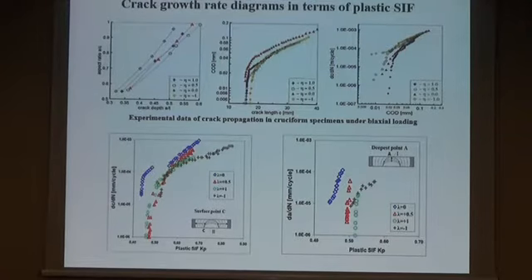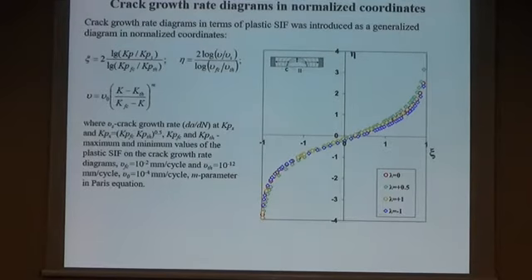So I believe that this result demonstrates the advantage of plastic stress intensity factor application as a characteristic of fracture resistance material properties. And crack growth rate diagrams in terms of plastic stress intensity factors in this study were introduced as a generalized diagram in normalized coordinates. So you can see that experimental data for different types of biaxial loading remain in a narrow scatter band, and such a generalization allows us to obtain a single curve that describes a strong correlation between crack growth rate and plastic stress intensity factor.